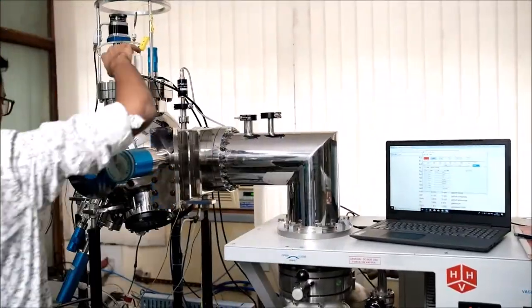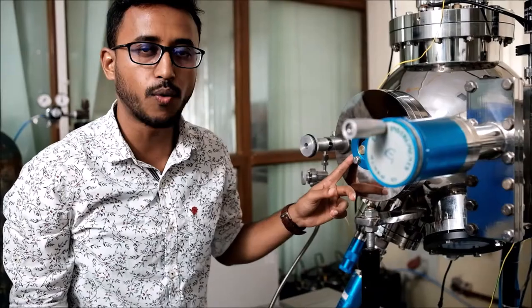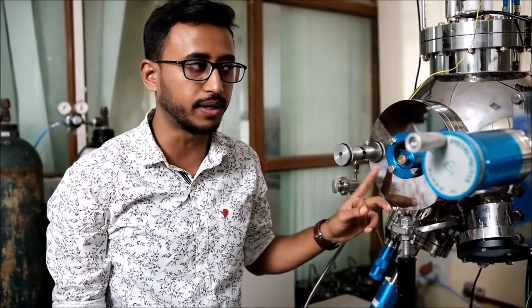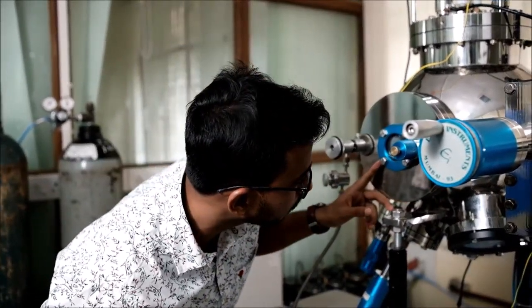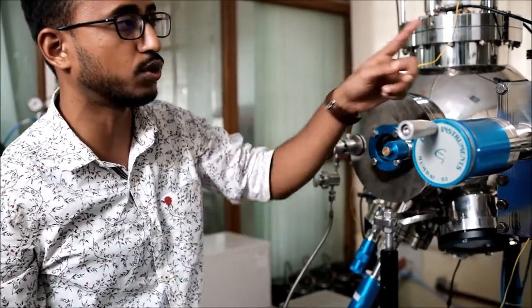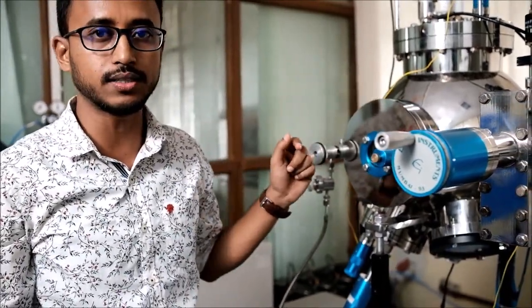So now, as you can see, the plasma is directly falling onto the substrate, and also the substrate is rotating at 20 rpm speed. And I want my deposition to occur for 30 minutes. So after 30 minutes, I'll stop the deposition and also the QCM, and I'll see what thickness we get.